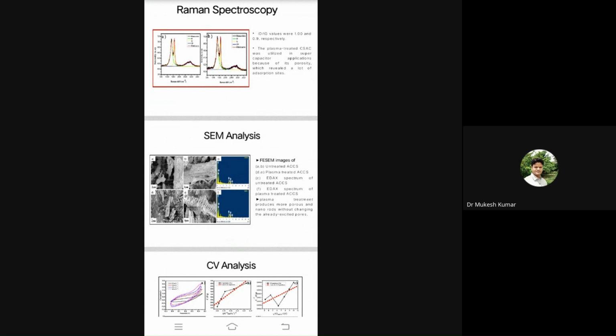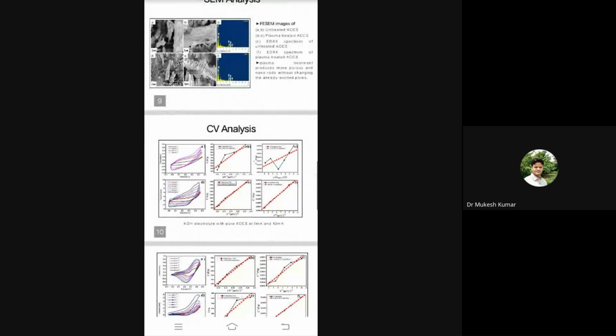The plasma treated cotton stalk was utilized in supercapacitor applications because of its porosity, which provides a lot of absorption sites. Next, we see the same SEM analysis. The SEM images: A is the untreated activated carbon, and D is the plasma treated activated carbon. The EDAX spectrum C is the EDAX spectrum of untreated activated carbon. Then F is the activated carbon after the plasma treatment.